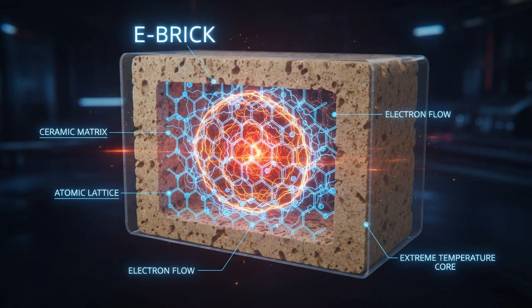They stop electricity, but ETS realized that if they doped these bricks with specific metal oxides, like adding small amounts of nickel to chromium-based ceramics, they could change the material's properties at the atomic level. This doping process creates defects in the atomic lattice of the ceramic. These defects act like stepping stones, allowing electrons to hop from atom to atom. This phenomenon turns the brick itself into a resistor.